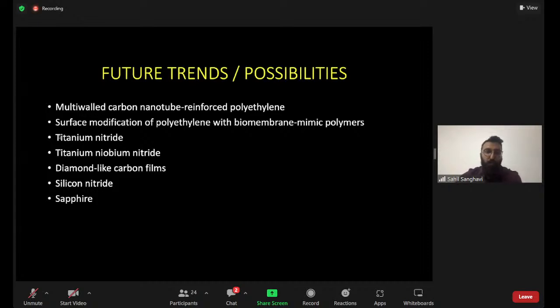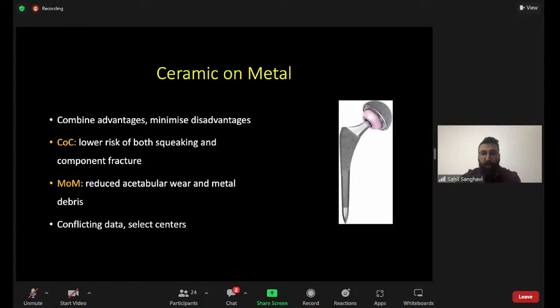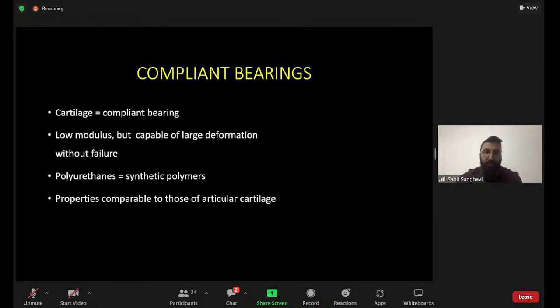What are the future trends or possibilities? Implants like titanium nitride or titanium niobium nitride, diamond-like carbon films, sapphire, or silicon nitride. There is also some research going on for ceramic on metal because they're trying to combine the advantages of ceramic, minimize squeaking and component fracture, and at the same time use the advantage of metal of reduced acetabular wear and reduce the metal debris. However, there's only conflicting data, and this is being used only in a few select centers. Again, compliant bearings are being tried where they're using polyurethanes to mimic human articular cartilage.